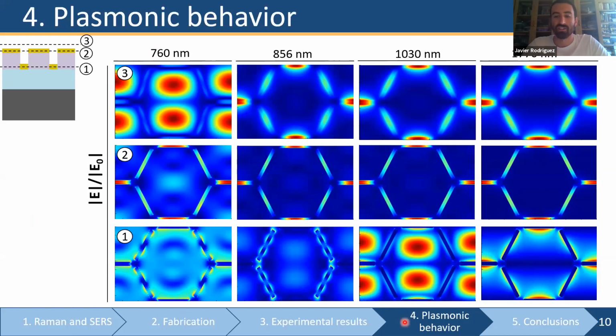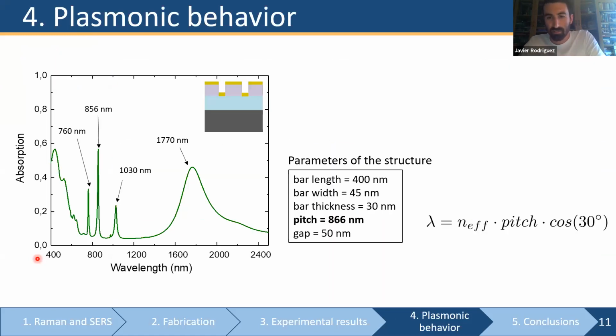Unfortunately, this collective excitation is not of any use for the Raman or sensing purposes, since the electric field is concentrated in the bottom structure, and this electric field distribution is happening inside of the silicon oxide. So it's not accessible for a molecule from the outside. So now you may wonder, why do we precisely have these collective excitations only in these two wavelengths, and only in the top structure for the 760 nanometers, and only in the bottom structure for the 1030 nanometers? Well, it may be clearer if we take a look at this explanation.